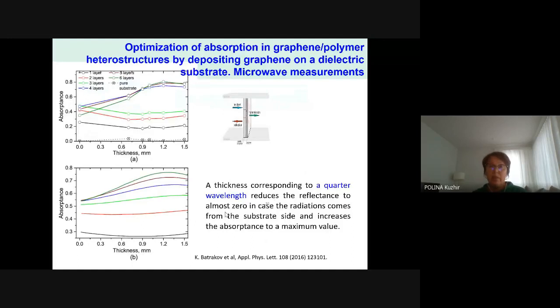But immediately we start to think how to enhance this absorption ability, and the simplest way is to put this graphene sandwich structure on top of a dielectric slab corresponding to a quarter wavelength. According to both theoretical estimations and experimental data, with this we could go up to almost perfect absorption.